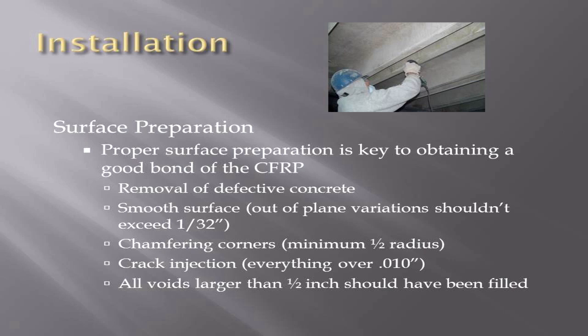Also, crack injection. Most people recommend a 10/100ths crack injection for your minimum crack size you have to inject prior to installing FRP. However, some manufacturers even recommend injection of even smaller sizes. All voids larger than a half an inch should have been filled with your putty during your surface prep. That's important.